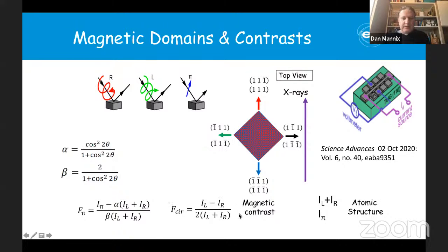We access this magnetic information by using what's called a flipping ratio. So we have a circular flipping ratio, which is the difference between left and right divided by the sum. That can give us some magnetic contrast for the moments in the magnetization in the scattering plane. We devised another one which can be used to access the one for pi, and that's this flipping ratio. And that will give us magnetization responses to the ones perpendicular to that direction. And if we simply take the sum, as I said before, we're left with the atomic structure. So in principle, using the same data sets of left, right, and pi, we can get information on magnetism in the scattering plane, perpendicular to the scattering plane, and correlate that with the structural one underneath, which is the atomic scattering factor, the normal one, by the sum.